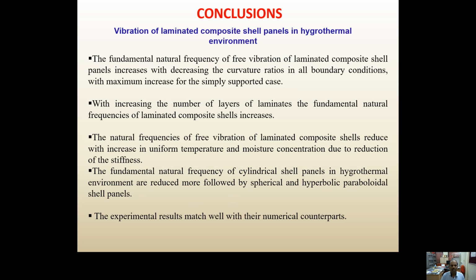Coming to the conclusion, the fundamental natural frequency of free vibration of laminated composite shell panel increases with decreasing the curvature ratios in all boundary conditions, with maximum increase for the simply supported case. With increasing the number of layers of laminates, the fundamental natural frequencies of laminated composite shells increase. The natural frequency of free vibration of laminated composite shells is reduced with the increase in uniform temperature and moisture concentration due to reduction of the stiffness. The fundamental natural frequency of cylindrical shell panels in hygrothermal environment is reduced more, followed by spherical and hyperbolic paraboloid shell panels. In all the cases, the experimental results match well with the numerical predictions.